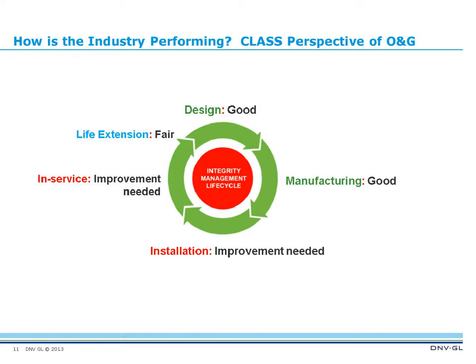So what is the reason for the generally high rate of failure of permanent mooring systems? Our offshore class perspective is that whilst design and manufacturing are generally good, more effort is needed in installation and in-service. In fact, installation is quite key, as in some failure cases, whilst the root cause analysis showed that the in-service was the failure cause, like let's say having too much wear between chain links, this may have actually stemmed from an installation problem. For example, there was twist in the chain causing the wear in the first place, but due to lack of proper documentation of the installation and rigorous survey, this was missed, and therefore the failure is wrongly attributed to in-service.